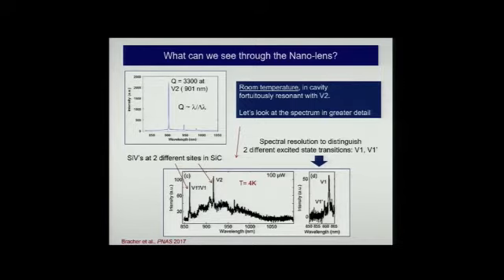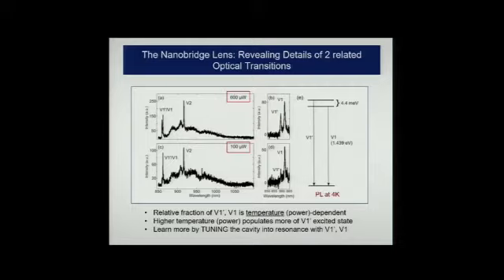That's interesting, but does it mean anything? Well, if we actually make measurements, we make the same measurements, and again, this is untuned. We do one measurement with the incident laser power, 600 microwatts. We do another measurement with a slightly lower incident laser power. Notice, and this is not a fluke. This is reproducible.